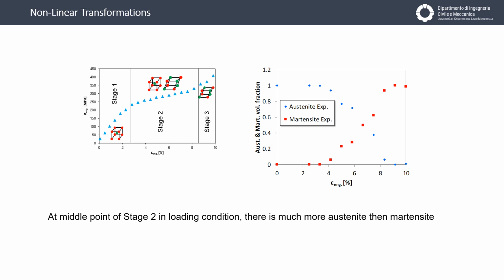Furthermore, from the spectrum it is possible to calculate the quantity of the austenite and martensite present in the material, and in this case the results are reported in the graph on the right. You can see that the material is fully austenite, and then the quantity of austenite decreases down to 0. And the transformation of austenite into martensite is similar to a mirror, and we have an increase of the martensite up to 1. The transformation is not linear, as you can see here.